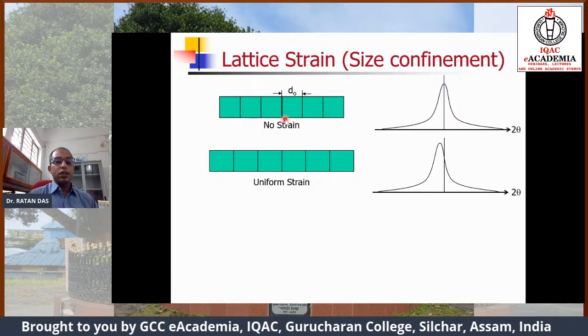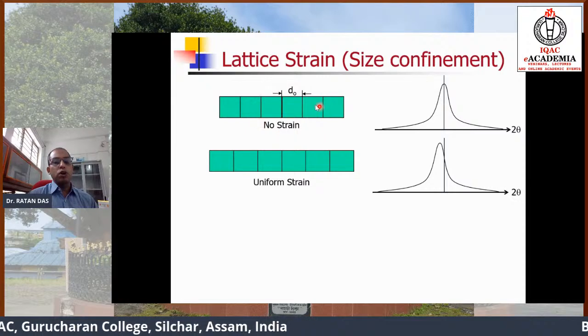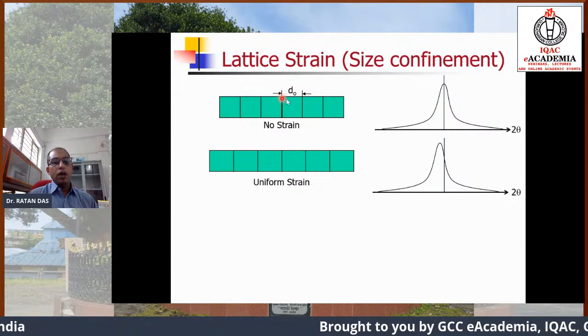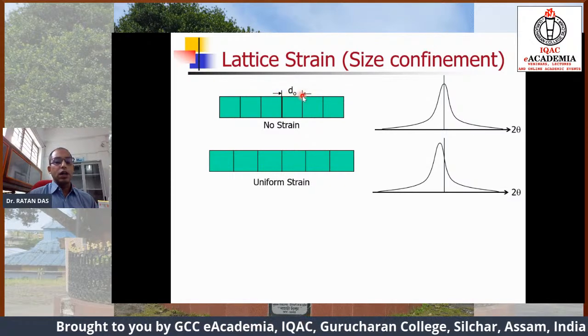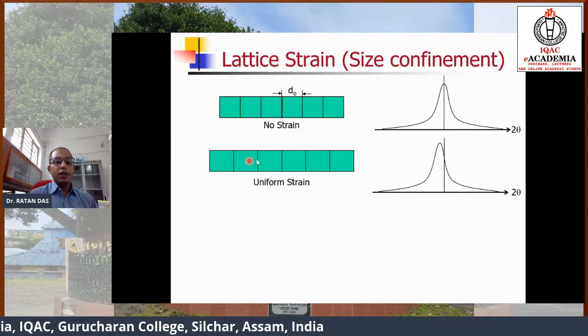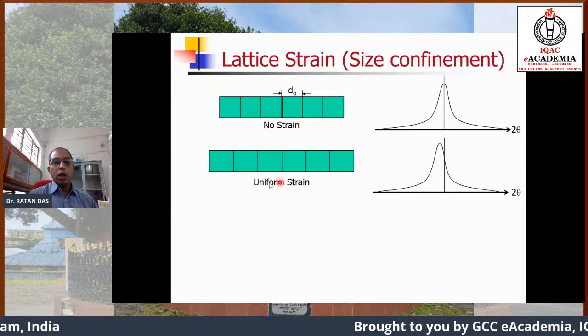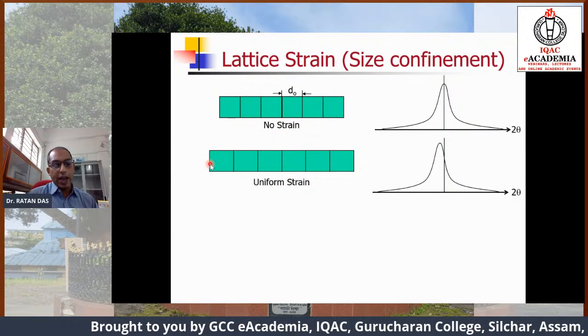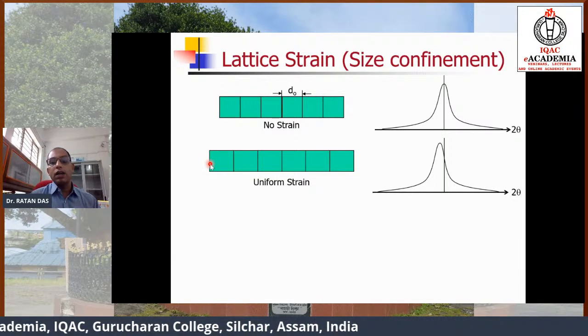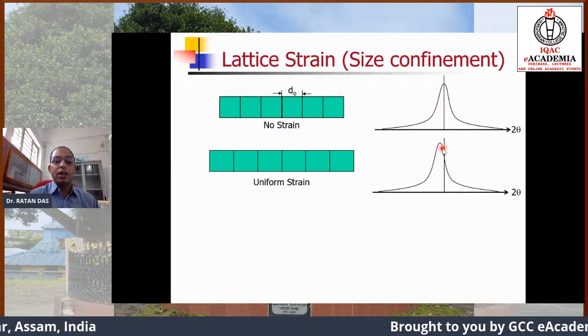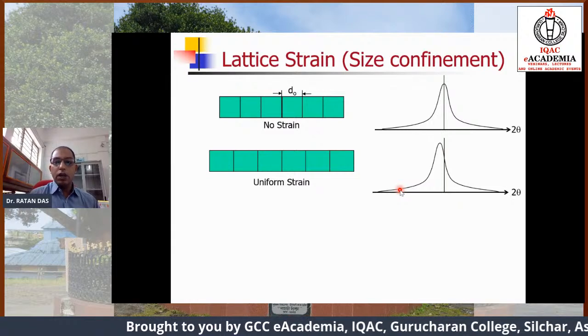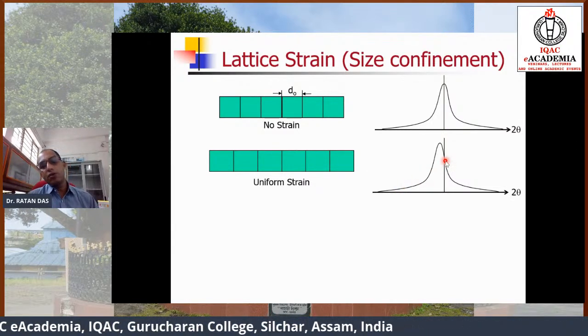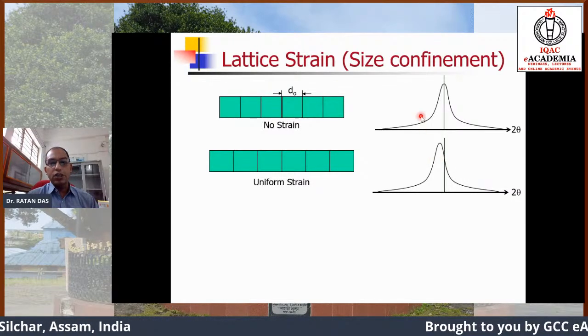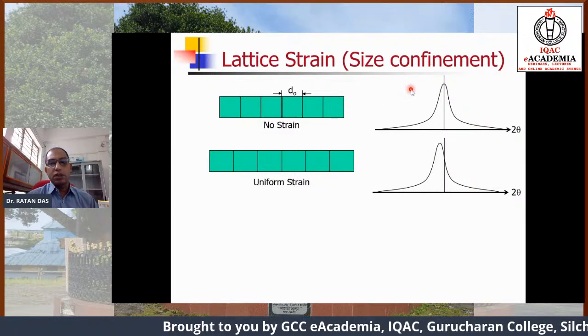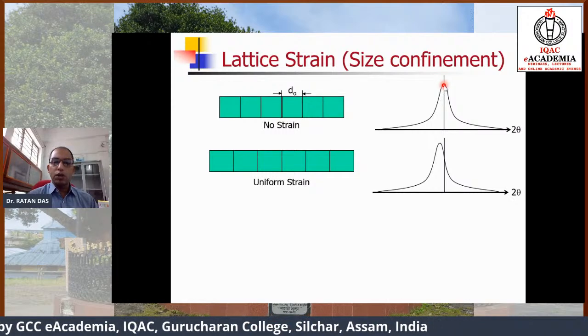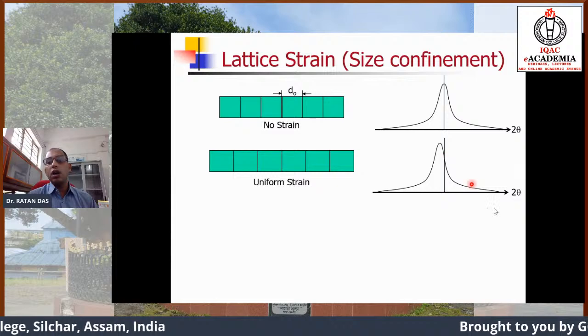You see here, suppose this is a bulk sample where this is the lattice pattern, and it is the lattice distance d. But if we go into the nano range, then there may be an increase in the lattice distance because of the size confinement, and because of this lattice expansion, the peak position may get shifted. I shall explain why the peak position may be shifted to the higher two theta or lower two theta range. A bulk sample may show you a particular two theta value, but because of the size confinement, there will be some shift of the two theta value.